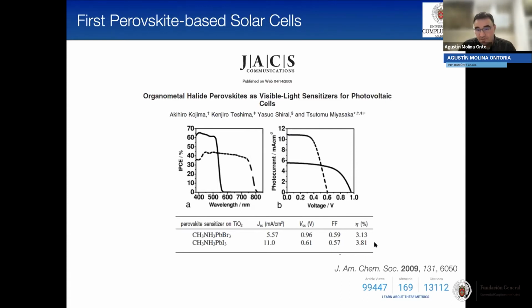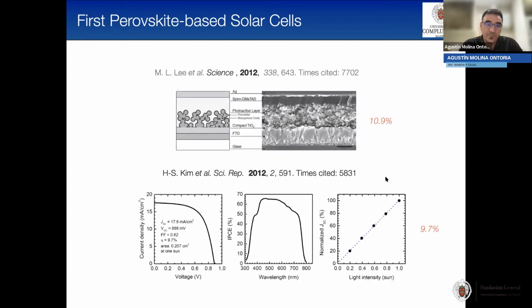So they got very modest efficiencies, around 4%, but the problem was not the modest efficiency that they obtained. The problem was the stability, because the device didn't last for more than 5 minutes. Why? Because the liquid electrolyte degraded the perovskite. Well, this was a very relevant work, as you can see from the number of citations, more than 13,000 citations.